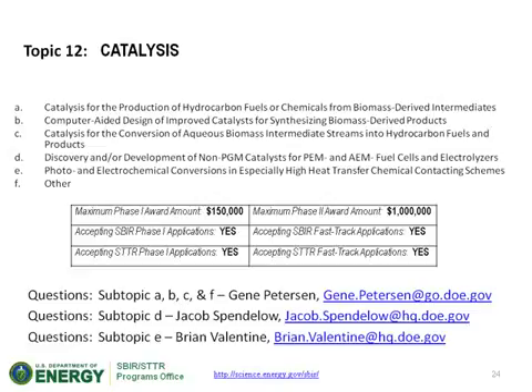In particular, we're interested in catalysts that demonstrate activity meeting the DOE targets, which are 300 milliamps per square centimeter at 0.8 volts. To meet this target, both high catalytic activity and good mass transport properties are needed, but there's more of an interest in the catalytic activity at this stage. And we did receive a few questions about this subtopic.